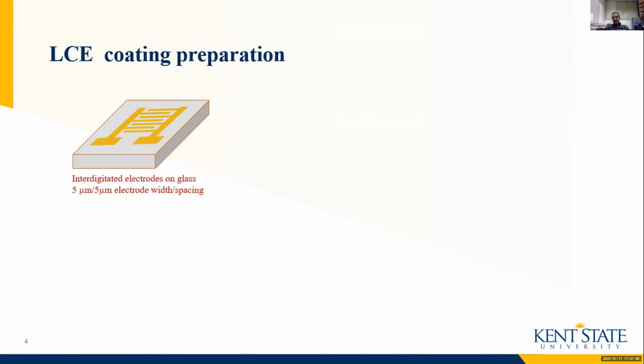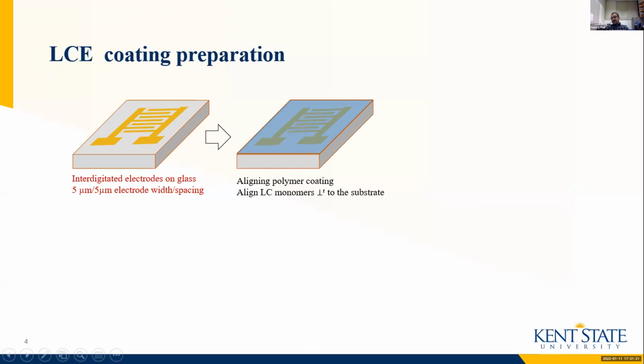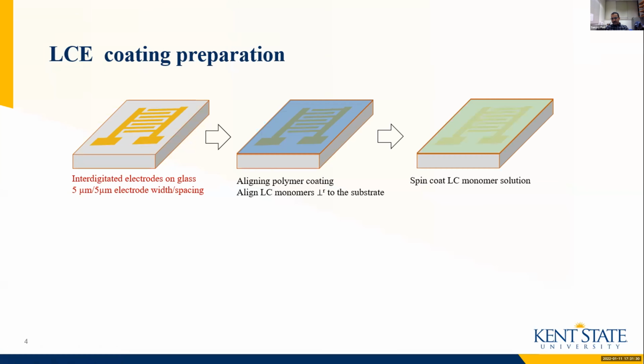To study the liquid crystal actuation under an AC electric field, we consider an interdigitated electrode substrate. The electrode width is 5 micron and spacing 5 micron. We coat this substrate with an aligning polymer that aligns liquid crystal monomers perpendicular to the substrate. Now, we consider the mixture of monoacrylate and diacrylate liquid crystal monomers and dissolve it in a solvent like dichloromethane and make a uniform mixture.